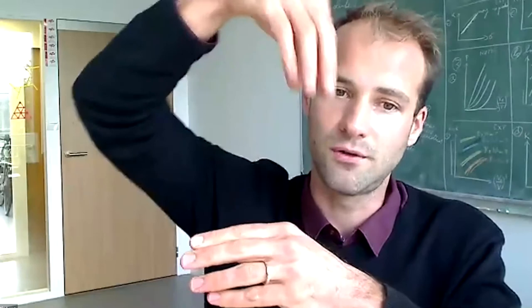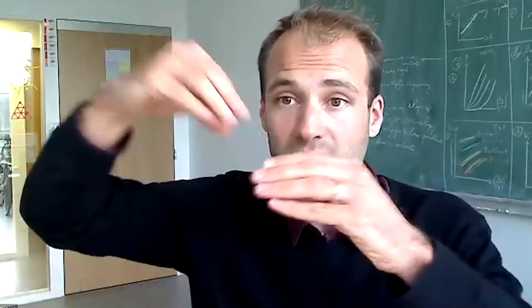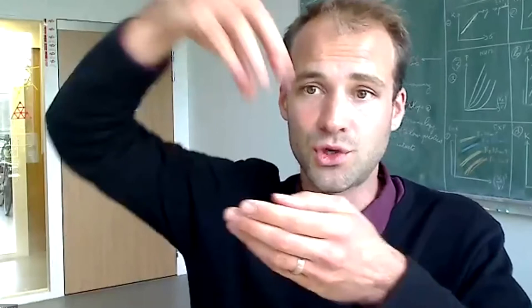And you can imagine that if you come in with a fourth particle, a fifth and a sixth, every time the problem is going to be more and more geometrically constrained. So you might imagine that as you build up the aggregate, the aggregation becomes energetically less and less favorable. And maybe at some point it will become so unfavorable that it's not going to be a good idea to come from the solution and into the aggregate anymore, but that the aggregation is going to stop. So that's the first part of the argument. That's the part of the argument that tells you maybe that buildup of geometrical frustration will result in an aggregate that has a limited size.